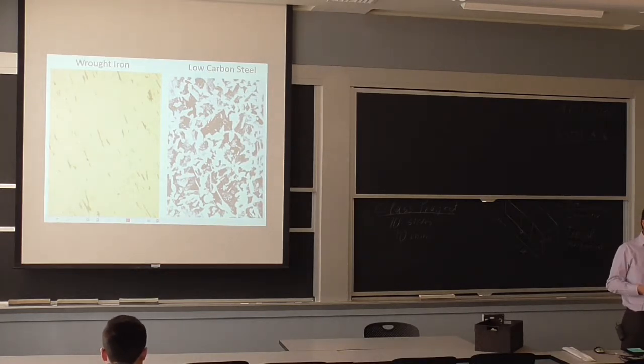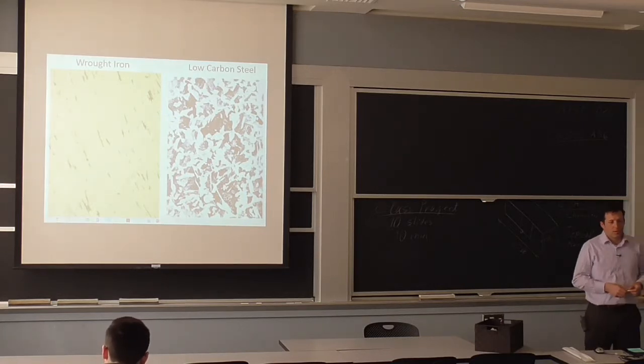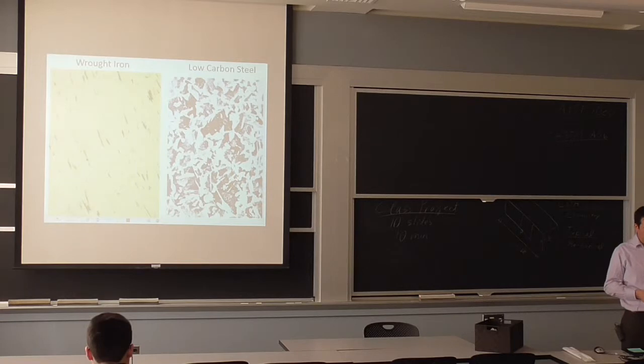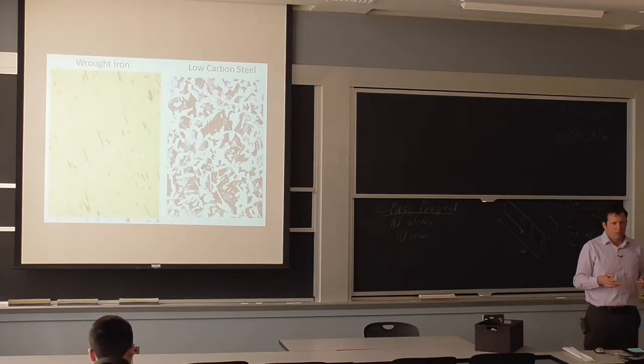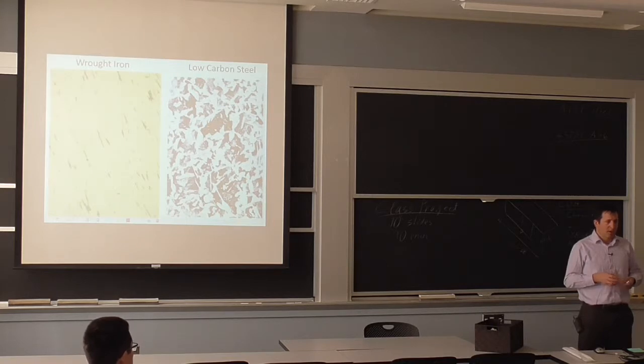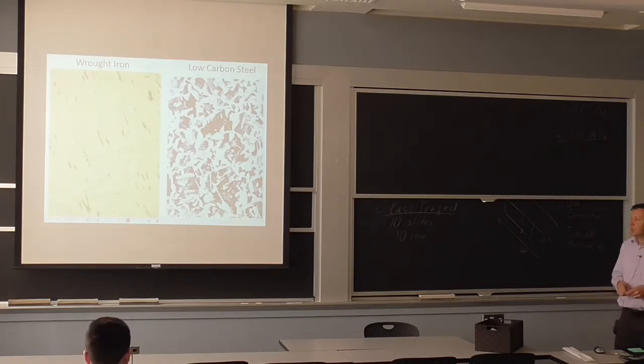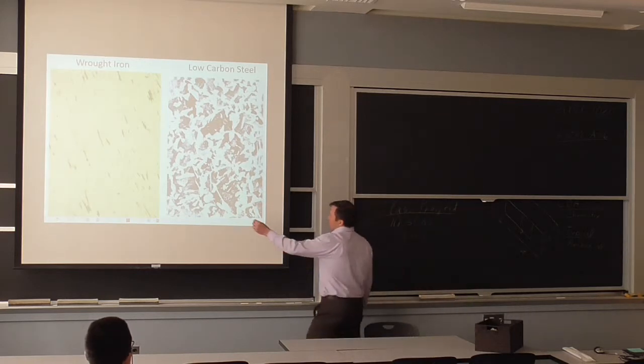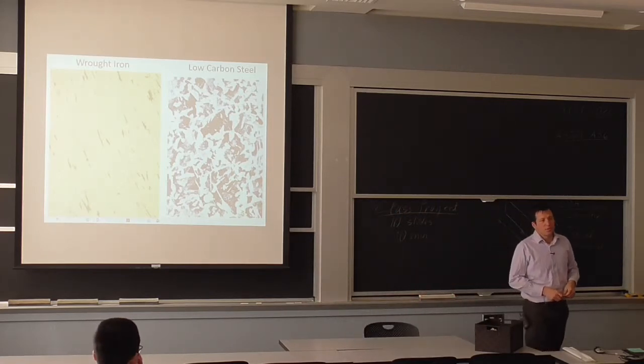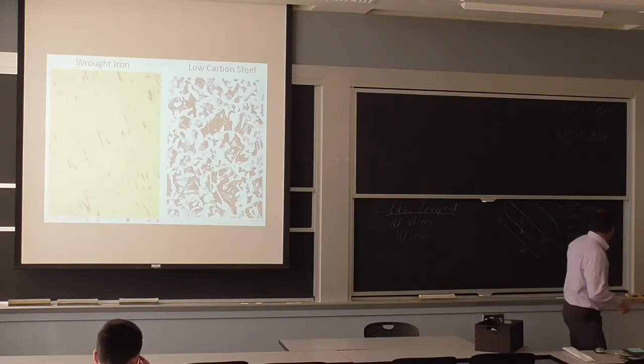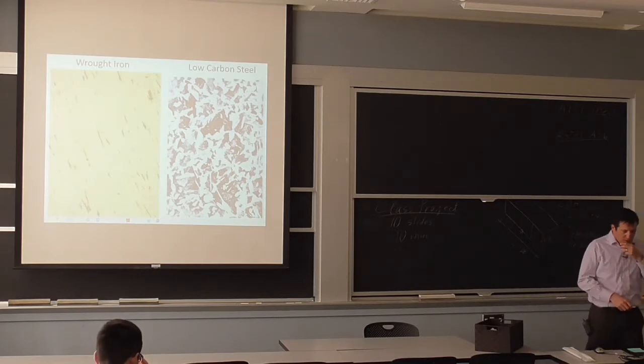So everything built, say, starting around the beginning of the 1900s, should be steel. But it points to something that happened to me once where we suspected it wasn't steel, it was wrought iron, just because there were a little bit more impurities than what we normally expect in modern steel. But it really wasn't a good way to tell, because the main difference is the microstructure, whether you have the carbide and the inclusion all segregated, or whether you have the pearlite here. So this is not just carbon-based Fe3C. This also has ferrite in it. It looks dark, but this is about the same composition. It's just the way it looks, and it points out that if you're going to ask just for chemistry, you don't know what you're getting.